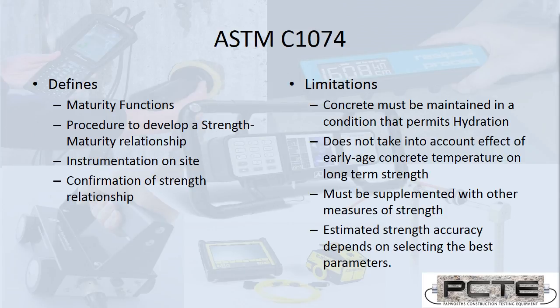Now, it also mentions specifically limitations of the technique, and these are quite important. The technique assumes that concrete is continuously hydrating. If there is something that prevents the hydration of the concrete, very low temperatures, or lack of moisture, improper curing, a temperature measurement for maturity may not capture the real strength of the concrete, because if we've lost moisture and the concrete cannot gain hardness due to the loss of moisture, that relationship is now of concern. It also does not take into account the effects of those early age strength gains on the final strength of the concrete. One reason why a 28-day cylinder should still be used. And the final thing is, it's the quality of the curve creation that is going to control the quality of the eventual maturity relationship and how it's used.